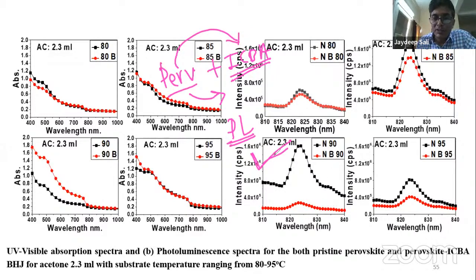So this figure tells that if you simply take perovskite, then the photoluminescence intensity is high. But if you prepare a blend of perovskite and ICBA with the method that I have just explained, then there is a significant reduction in the photoluminescence intensity, indicating efficient charge transfer from perovskite to the second phase. And this type of charge transfer is essential. It is needed for efficient performance of a photoactive layer.